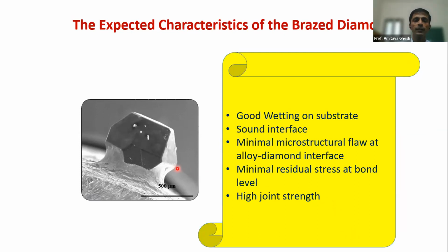To braze diamond to a steel, we need certain typical characteristics. Number one, the alloy needs to nicely wet the substrate. Generally, we use a metallic filler, so metal-to-metal spreading is very easy. But as far as wetting of this alloy on diamond is concerned, it's pretty critical. We need to understand the metallurgy to make it more and more efficient. There should be a sound interface. When this alloy is wetting the diamond, the interface should be flawless, in the sense of having a minimal amount of microstructural flaws.